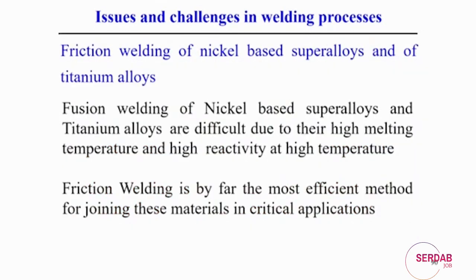Another issue in welding is the friction welding of nickel based super alloy and titanium alloy. For this type of material we generally use friction welding. Of course, fusion welding of nickel based super alloy and titanium alloy is very difficult because of their high melting temperature and, at the same time, high reactivity at very high temperature. That is the limitation of using fusion welding for nickel based super alloy and titanium alloy. So friction welding is the most efficient method of joining these materials in very critical applications, for example in the aerospace industry.